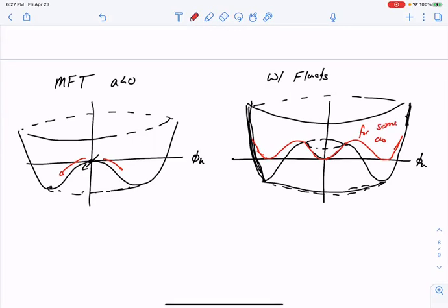So this is an example of a so-called fluctuation-induced first order transition, where the mean field theory would predict that I can spontaneously break continuous symmetry, ordering along this specific finite wave vector. Including fluctuations by finding an approximation which is Gaussian and optimal, one sees that the stability of the disordered state, owing to these huge numbers of fluctuations associated with the order parameter field, is always stable. And thus I go through a first order transition to abruptly break continuous symmetry, like one might have expected, given the first part of our discussion.